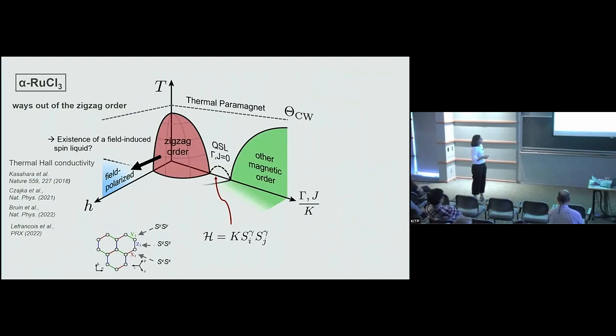Here would be our system, and one option is to apply a magnetic field, just suppress the long-range order, and then see whether, by suppressing long-range order, one reaches a state which is a quantum spin liquid before going into the field-polarized phase. This is the region mostly debated in alpha ruthenium trichloride, and there were many talks and discussions. I'm not going to go in this direction because there is still a lot of discussion, and what I would like to present here is an alternative to that.